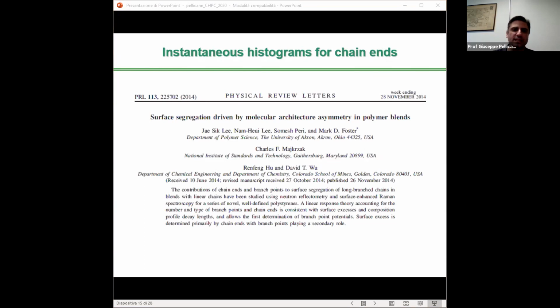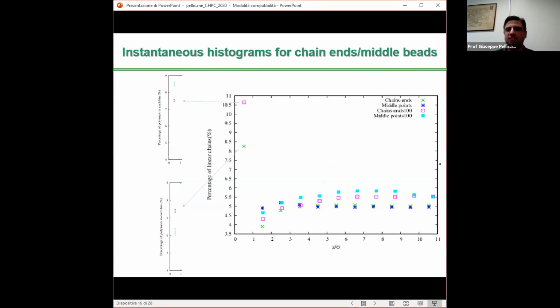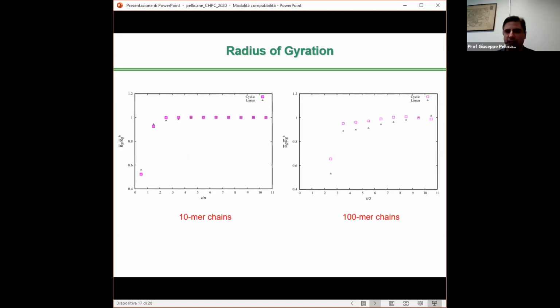So we had a look at the instantaneous histogram targeting chain ends, and the results seem to corroborate that chain ends get preferentially adsorbed at the interface. What we know is that the higher concentration of chain ends is found in the case of longer chains, while the percentage of linear polymers enriching the interface is almost unaltered.